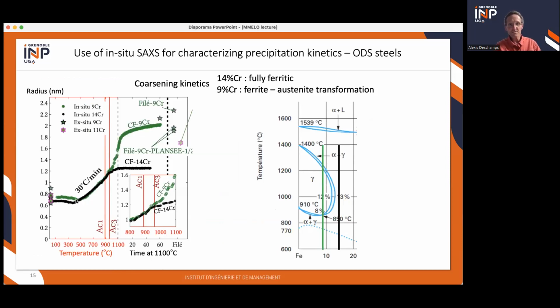The first one is that when you heat, let's look at this 14 chromium ODS steel. So 14 chromium is basically a steel that remains ferritic at any temperature during the process. Then initially you have some clusters that you can also image by atom probe. And right from about 500 degrees, you see that precipitates are forming from these clusters and growing, well, relatively fast until you get to 1100 degrees Celsius. At 1100 degrees Celsius, quite interestingly, they stop to grow. And despite the very high temperature, the thermal stability is just amazing. They stay at 1.2 nanometer for more than 1 hour at this temperature. And so this was really the finding of this in-situ kinetics.